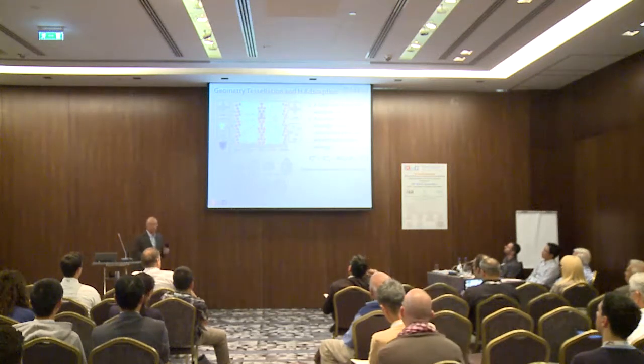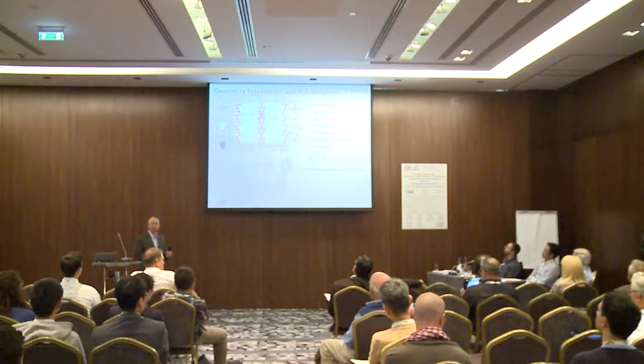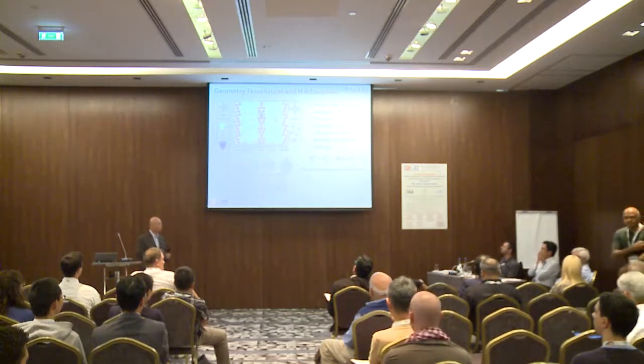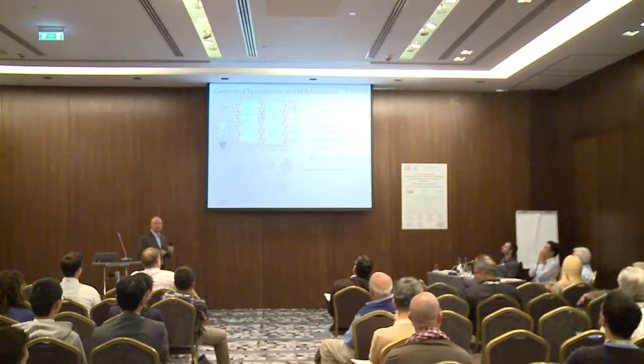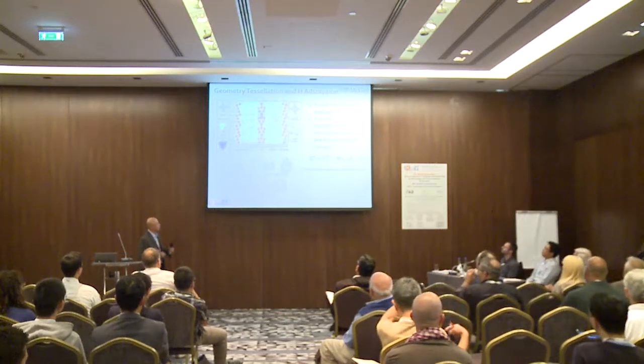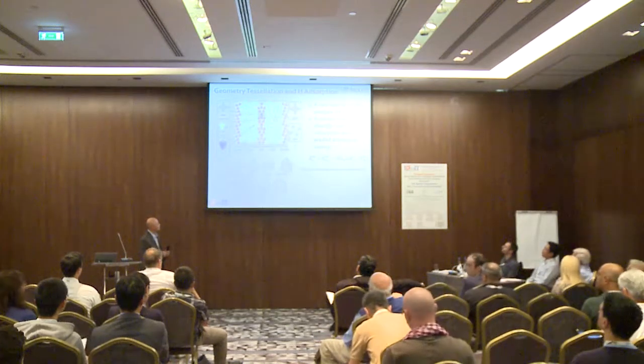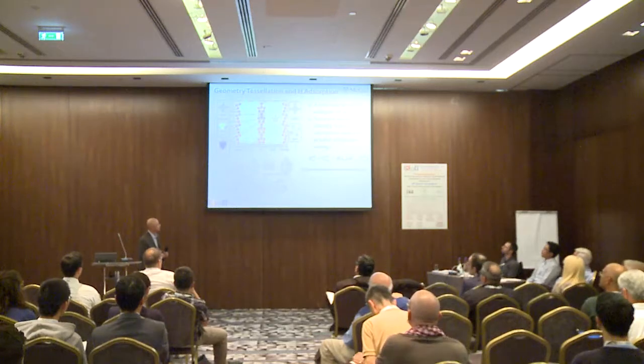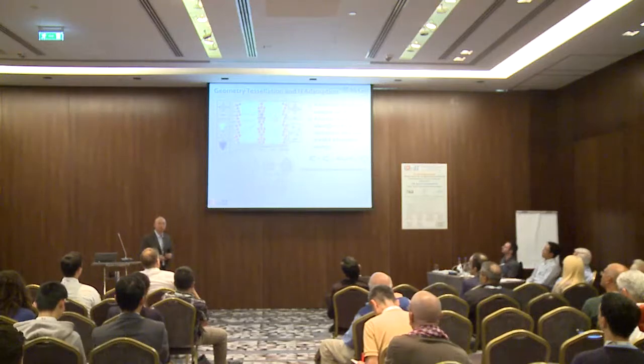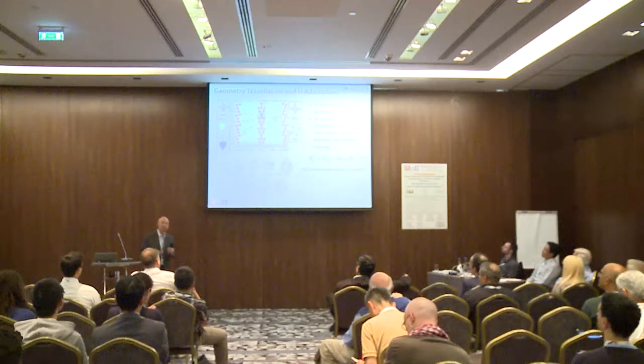Okay, so this method basically provides a very quick way to analyze grain boundary structure, and then combined with DFT calculation, you can quickly get the energetics of hydrogen absorption along the grain boundary or in the bulk lattice, as well as the migration barriers along grain boundaries. So this was published before, in a separate study, but I just want to give a background. This is basically the method we're using. It's kind of like a space tessellation combined with DFT calculations.